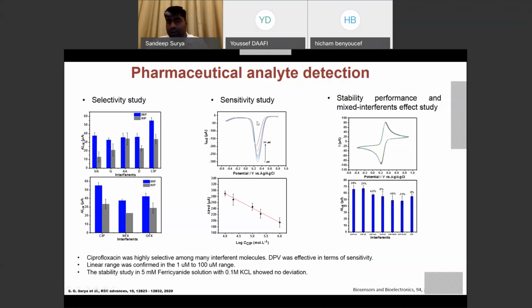Further going ahead, we did sensitivity studies that you see in the middle. We varied the concentration of ciprofloxacin from 1 micromolar to 100 micromolar, and we have seen a linear increase in the reduction currents observed from the differential pulse voltammetry. The final being the stability performance experiments that we have done.